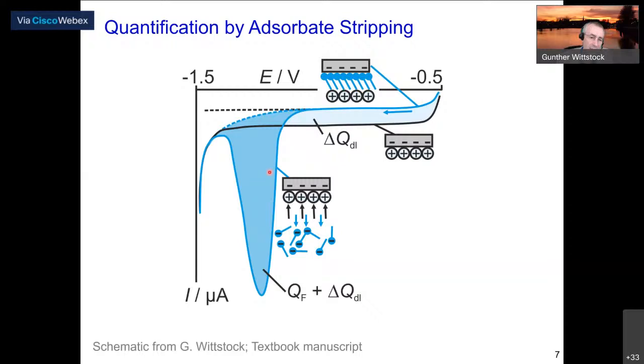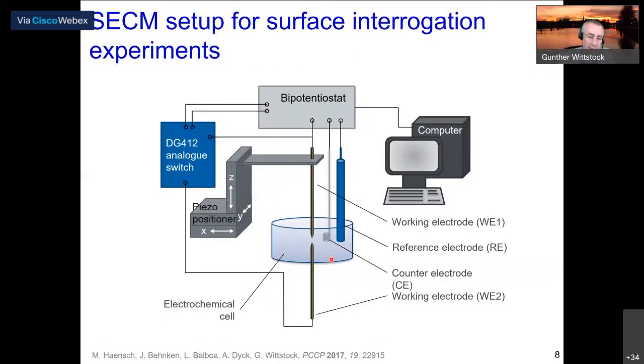So now in that peak, we have the charge for the Faraday process, but also the charge which was put into that double layer in all that potential scan from here to here. So at the same time, we get a change in the Faraday charge, but also in the double layer charge. And this is not easy to separate. So one way of doing that is to use the surface interrogation experiments of scanning electrochemical microscopy.